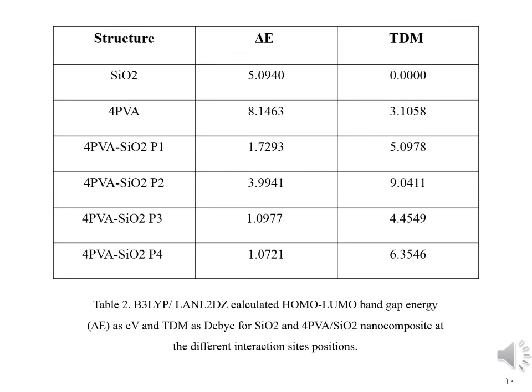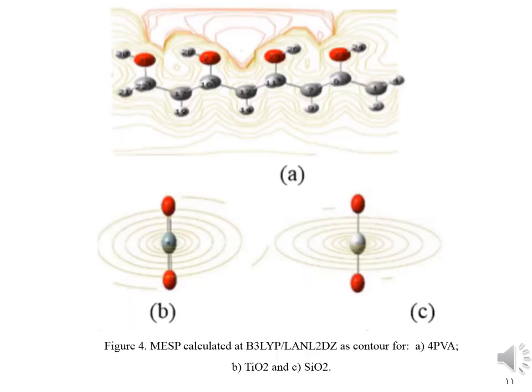The HOMO-LUMO energy decreased sharply and becomes 1.0721 electron volt for the interaction of silicon dioxide with 4 polyvinyl alcohol through the hydrogen atom linked to oxygen atom number 29. For the same interaction position, the total dipole moment of polyvinyl alcohol increased approximately to twice its value and becomes 6.3546 Debye. As we studied the HOMO-LUMO band gap energy and total dipole moment, we must study molecular electrostatic potential.